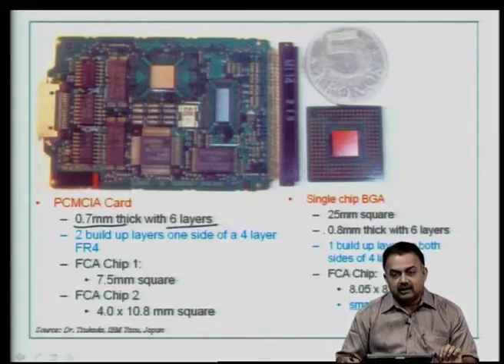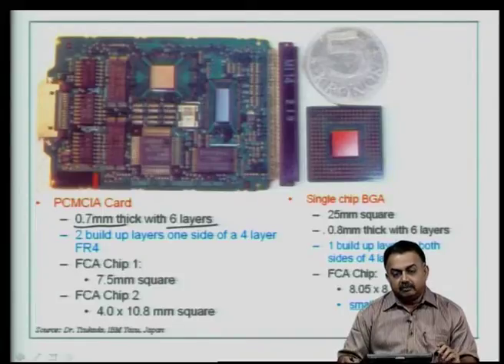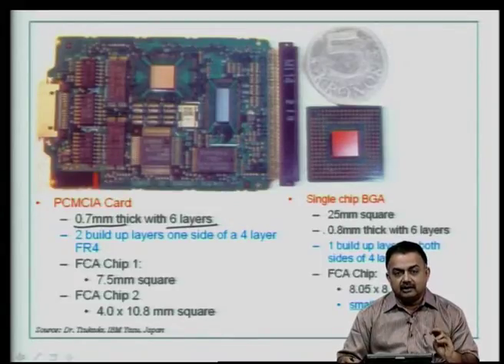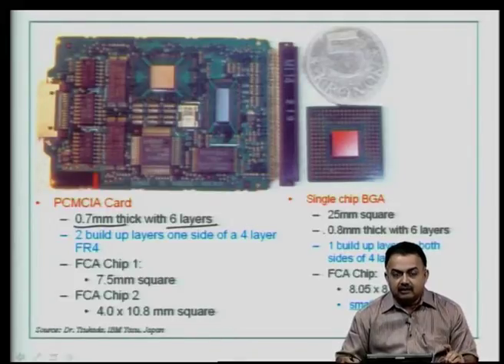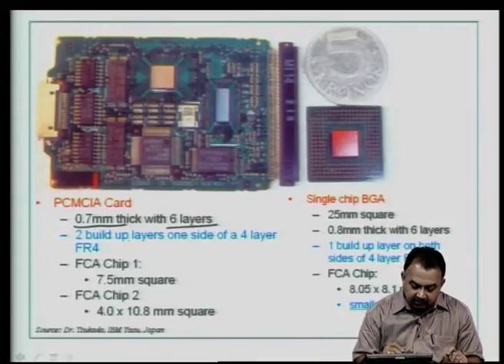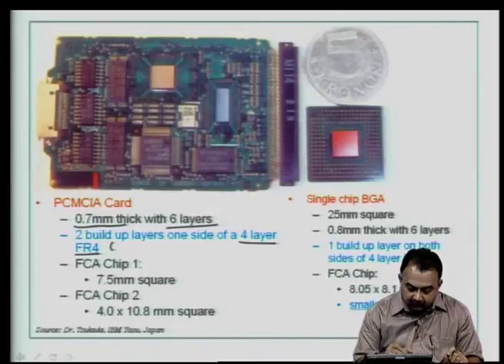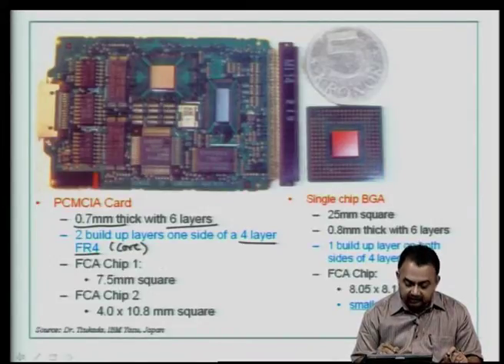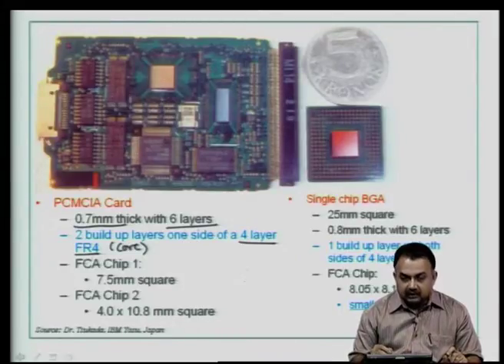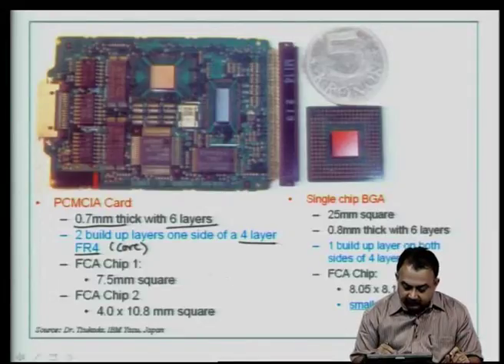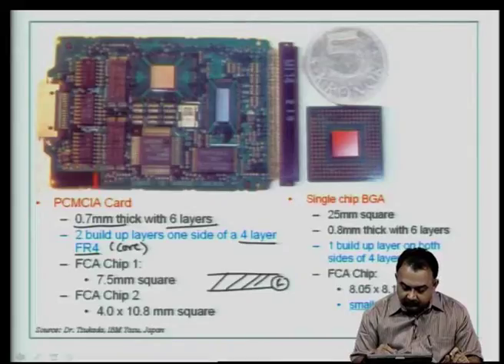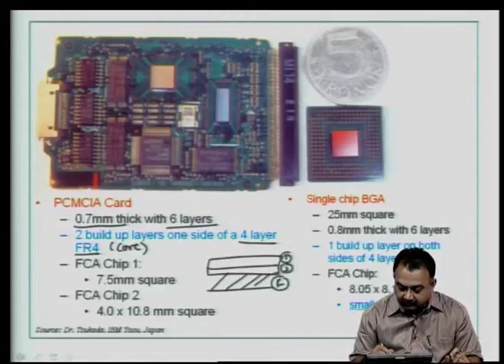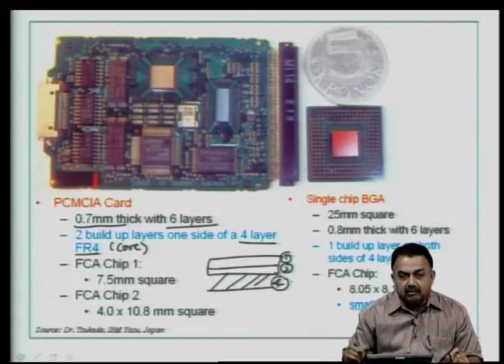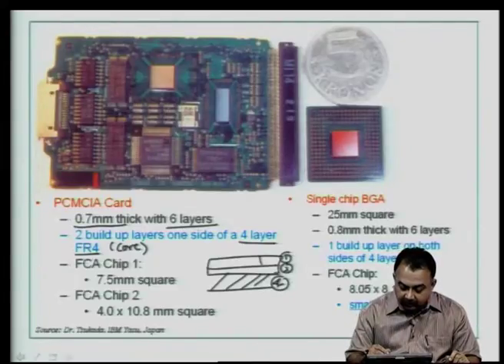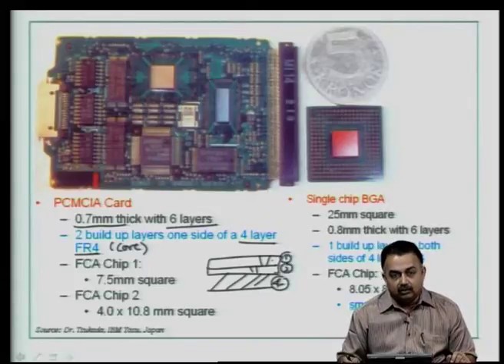So, 0.7 mm and then having 6 layers is not possible via the conventional multilayer board methodology, because the limitations are two. One is the prepreg thickness, the copper foil thickness that you normally get in the market, and third is the mechanical drill via size structures. So, in this particular example, 6 layer board, there is a 4 layer FR4 core that has been taken, and 2 build up layers have been created on one side of a 4 layer board. So, it is typically a design issue. It has been decided to have a 4 layer structure here, and then 2 layers have been built on one side. So, the other side did not have the sequential build up methodology at all.